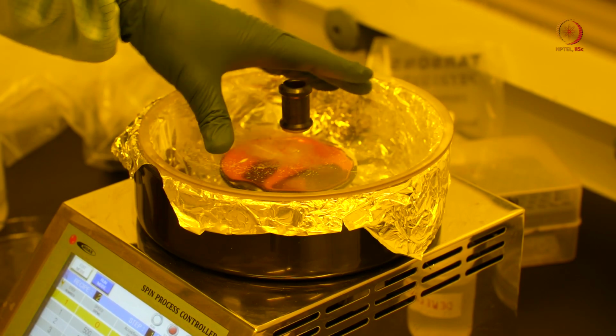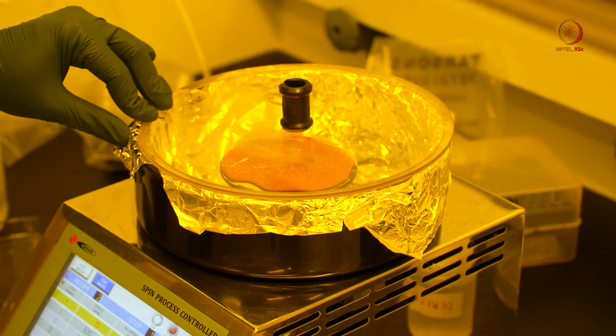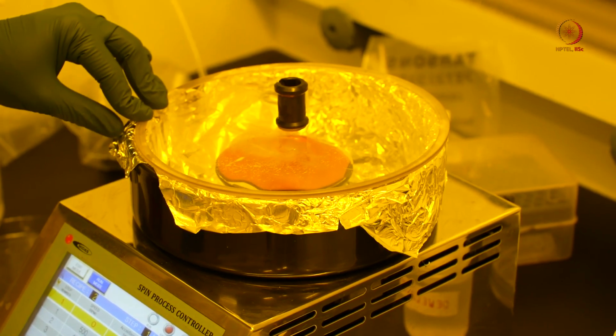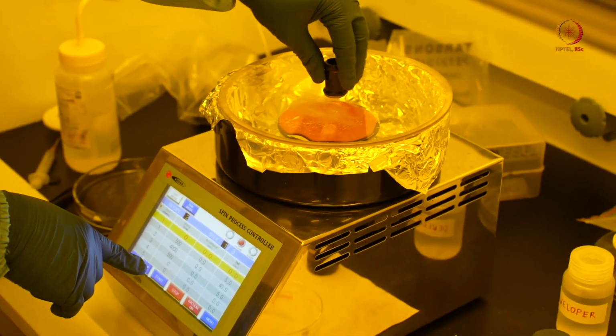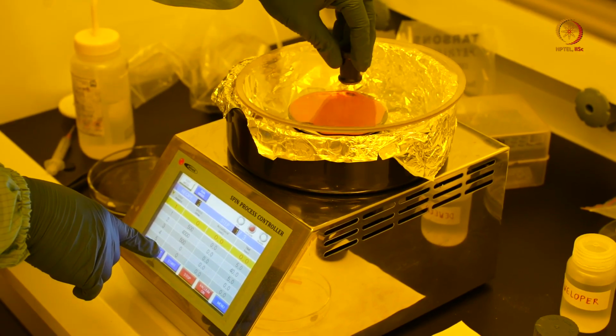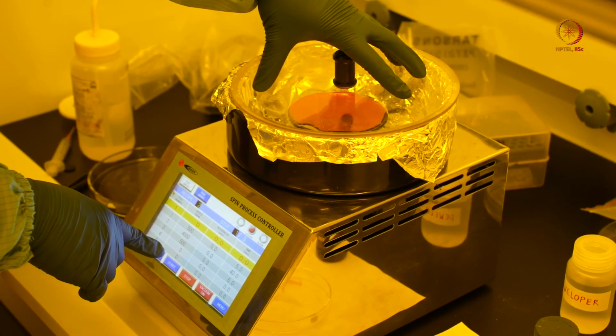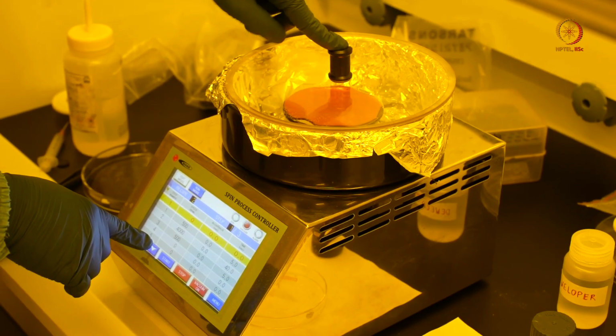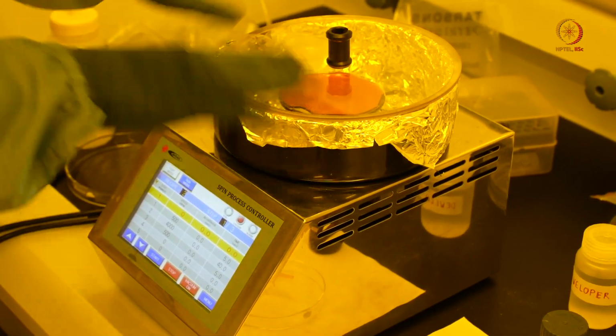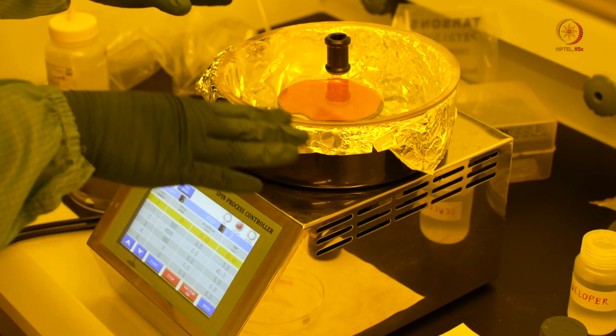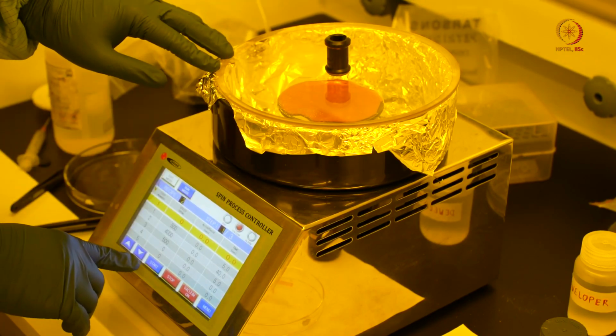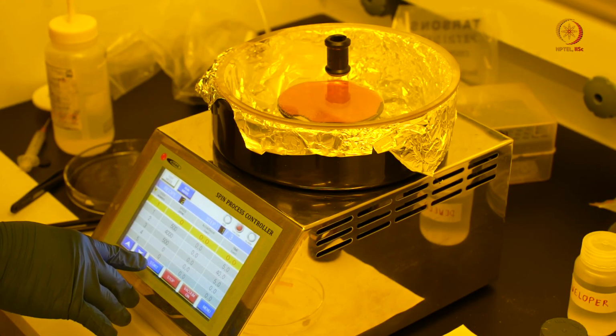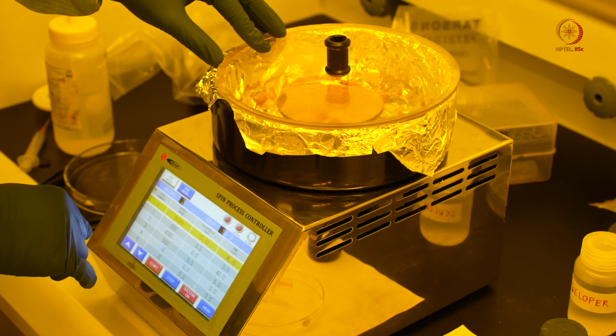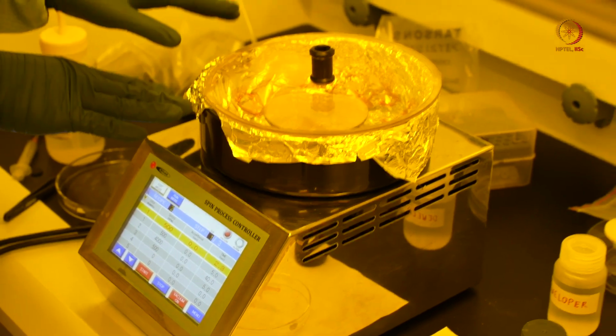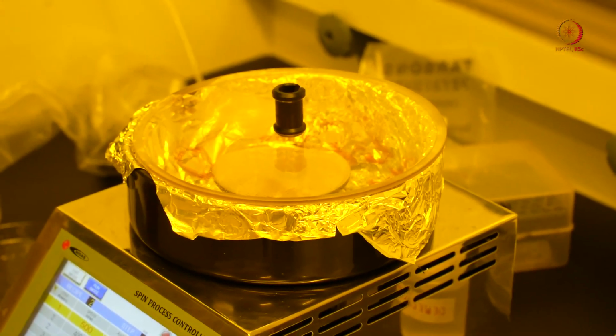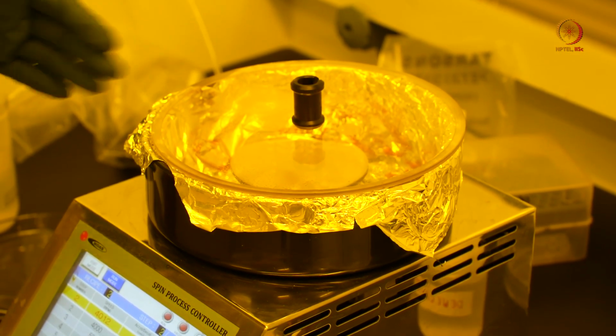So I'm closing the lid. The vacuum is already on. Then what we have to do is press start, and you can see inside it's a bit foggy, but you should be able to see through the glass lid how the wafer starts rotating, and the excess photoresist will fly away due to the centrifugal force, and a very thin layer will remain. It's a 40 to 60-second process. Now you will see the excess photoresist has flown away, and slowly the speed will increase to 4000 rpm.